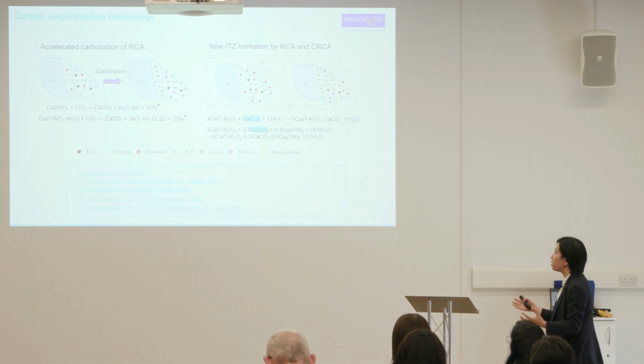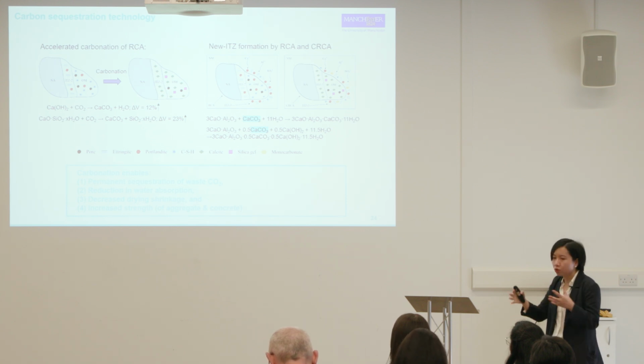During the carbonation process of reactions, the carbon dioxide reacts with the calcium hydroxide and calcium silicate hydrate to form the calcium carbonate and silica gel. And these two materials will fill the pores of the old mortar attached to the recycled aggregates. This old mortar layer is normally quite porous. After carbonation, the solid volume in this old mortar layer can be increased by about 12%, based on equation 1, and 23% according to equation 2.